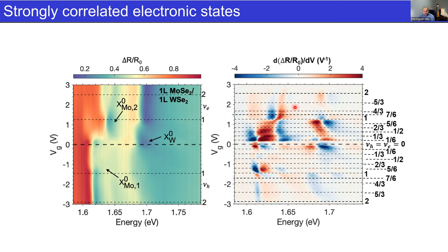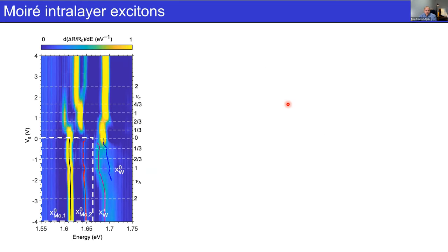So it's hard to interpret these features in this type of map. It's hard to get a sort of a physical intuition from this type of map, at least for me to read this. So we switched to plotting the derivative with respect to energy rather than voltage. So now we're more sensitive to the peak position rather than the changes as a function of doping. And in this picture, then we get a map that looks like this. So this is again the p-doping at negative and the n-doping at positive, where we've added in some of the lines from the other mapping of the different fractional fillings.